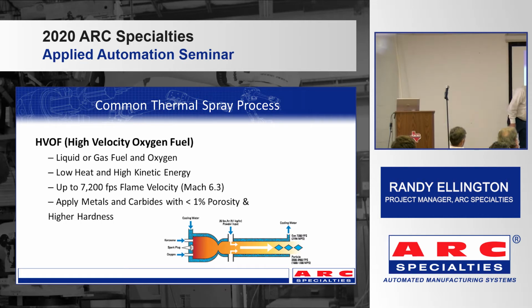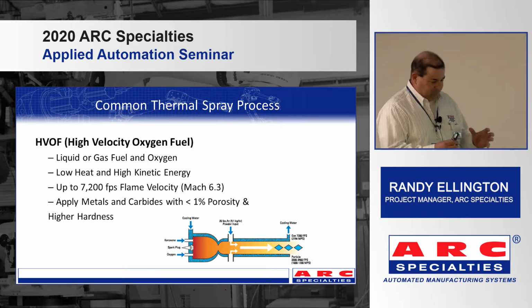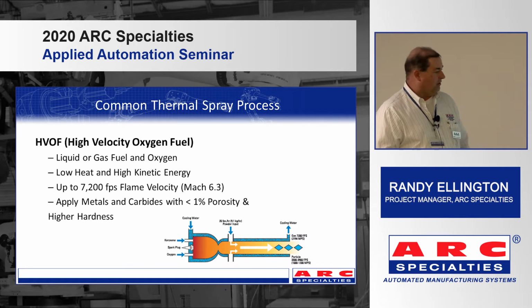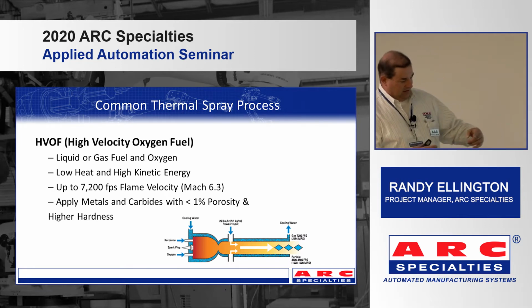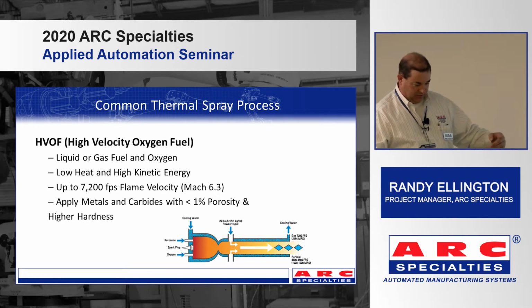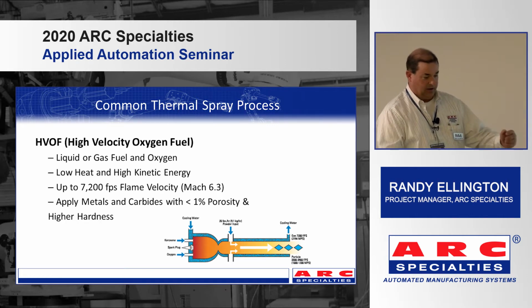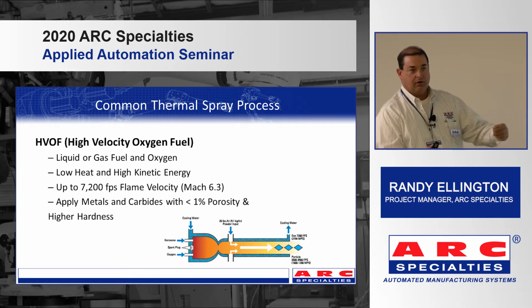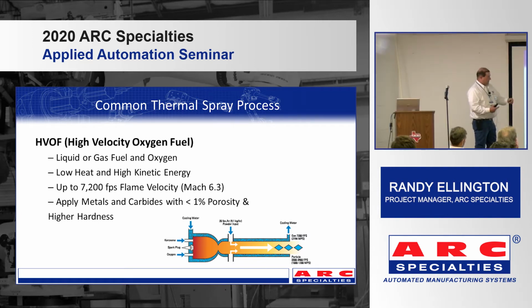You're injecting your fuel and your oxygen into a combustion can. You've got a small continuous combustion, usually around 120 psi. And then a converging diverging nozzle, which basically takes all that pressure, sends it down, and right as it's expanding, it creates a low pressure area where you can inject your powder. That's super critical. As that nozzle wears out, the pressure at your point of powder injection gets a little high, and then you start messing up the rest of the process. So the diverging nozzle, that's one of the more important things with that particular deal.